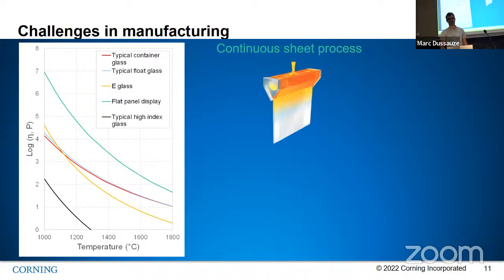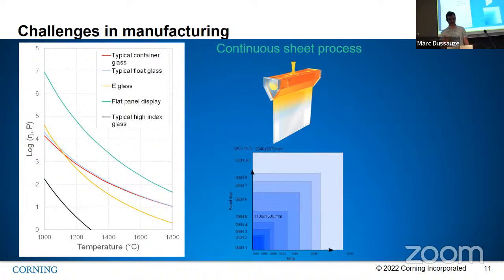For a display glass, we use the Corning fusion draw process, where basically we feed the glass from above, the glass overflows, and then from the two sides of this trench, the glasses are going to be fused, and you're going to make that pristine sheet of glass, which is very good to have some geometrical attributes, and it's very good because your glass is not touching any surface. So you make a very clean sheet, and that is how we were able to really increase the size of the flat panel that we can supply.